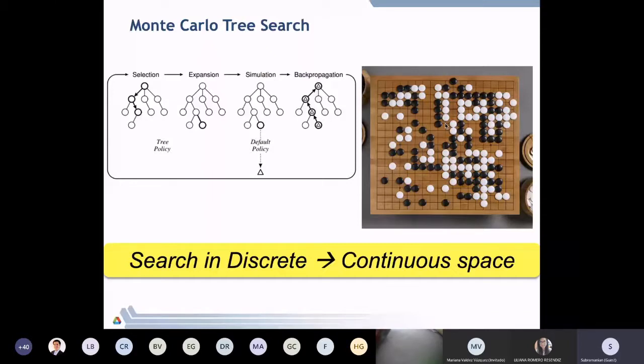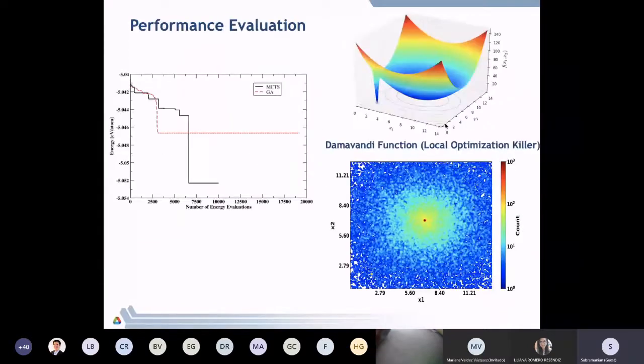So what we did, without going into the details of what changes we made, is we were able to bring about changes in MCTS, and we made comparisons to the genetic algorithm-based search. We looked at different trial functions, and MCTS outperforms GA in all the tests that we did. It basically finds a better minimum, and it is able to do that in fewer evaluations. So clearly, one can use MCTS for exploration of the potential energy surface.